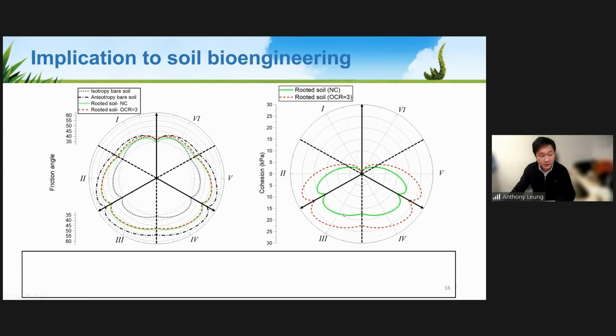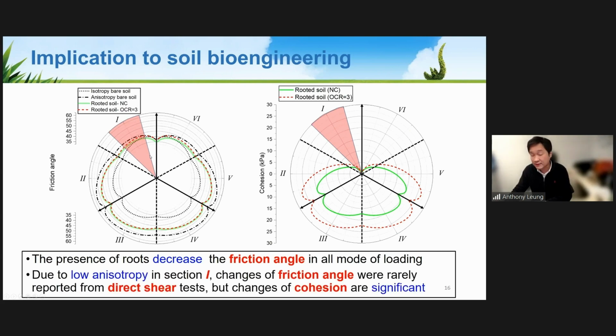So one important piece of information I want to highlight here: in the literature, we found in the direct shear box scenario, the friction angle didn't change much. That makes sense from our modeling because you can see the increase in friction angle here is only linked to this section 1, which represents the direct shear stress path. But if you look at the triaxial and extension path, the change in friction angle and the change in cohesion are much larger. So our model also can capture the direct shear loading conditions. So this could be quite a generalized envelope for rooted soil.